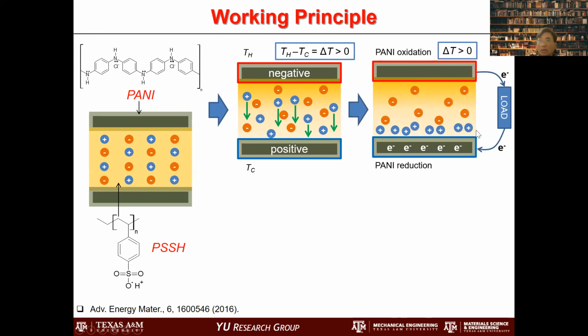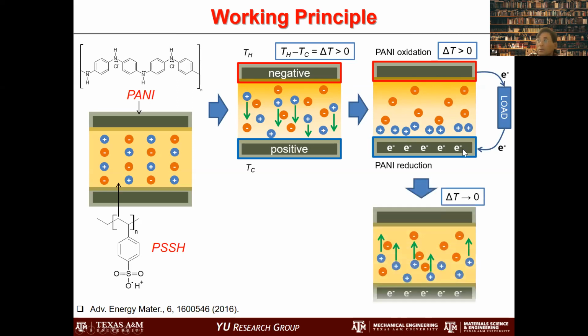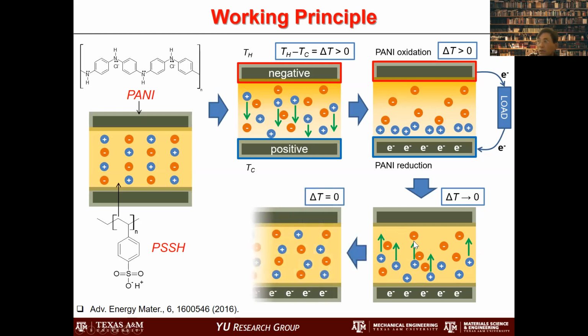And then these positive ions accumulate, and when we connect the circuit, since here's a positive, electron is withdrawn from the top electrode. That is because we actually have this polyaniline polymer, which can donate electron or receive electron. So it donates electron, and then this electrode receives electron. And then this electron will be accumulated on the bottom electrode. And when we turn off this temperature gradient, they actually return like this, and we disconnect the circuit. And then this electron is accumulated in one electrode. This is basically the energy storage. So this is basically the working mechanism.